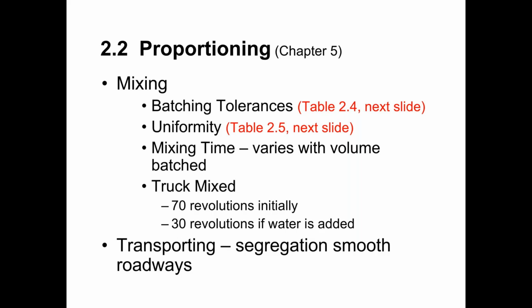So if I'm doing an audit at a plant that transports their concrete in mixer trucks so that they have this capability of adjusting the concrete at the bed, if I see them making any adjustments at the bed, then I'm going to be looking to see if they remix the concrete a minimum of 30 drum revolutions. So if I'm at your plant doing an audit, you transport concrete in this way, you make changes at the bed, then if I'm watching this while this concrete is being remixed, if you looked over at me standing to the side watching the process, I might look a little funny because my head is probably bobbing up and down.